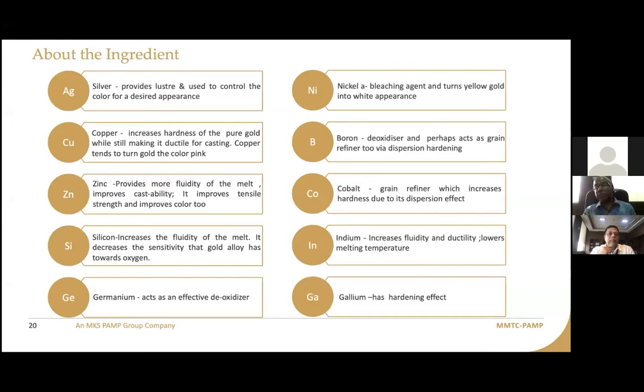It gives a typical color, but the zinc has to be maintained within a certain ratio. Otherwise, it will tend to form an oxide, which will exhibit as a defect when you try to polish it. So the balance is very important, how much zinc you are adding. Even extra zinc can lead to some losses during melting, which will actually lead to carat creep and is a concern, especially when you are working with higher caratage.